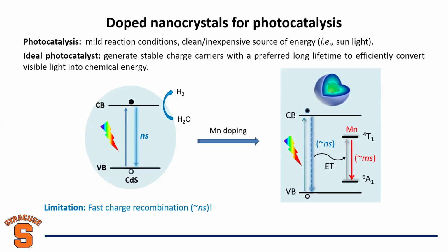Okay, milliseconds, 10 to the minus 3 seconds. You think it's still pretty short, right? But compared to the original nanosecond, 10 to the minus 9 seconds, you increase by 5 to 6 orders of magnitude. So we think the dopant can definitely provide much more stable charge carriers for further photocatalytic reaction. We have a much larger time window to use electrons for further reactions.